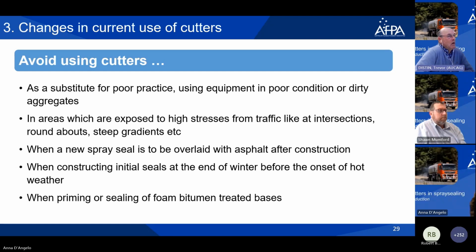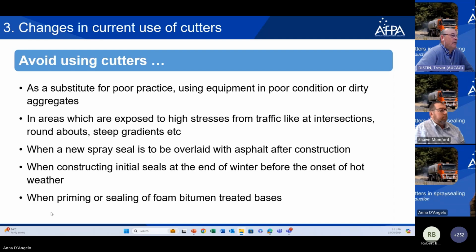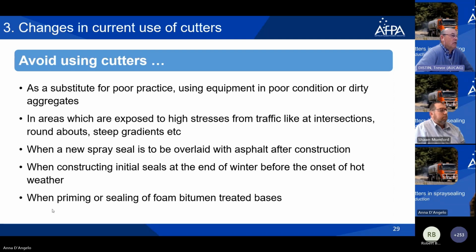And again, the waterproofing seal or SAMI seal that's placed under new asphalt, you want to eliminate any cutter there, so you don't trap the cutter in the seal, which will then possibly lead to softening of the asphalt overlay, which can potentially lead to rutting of the new asphalt under heavy traffic and hot weather.